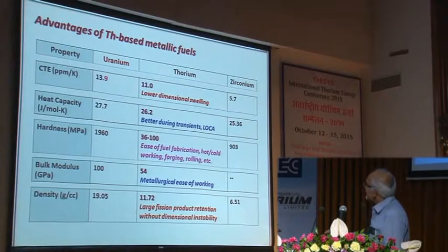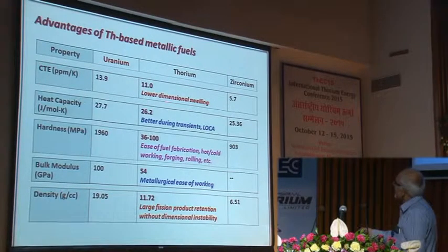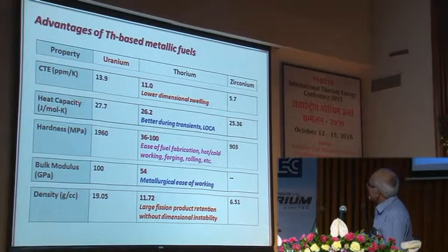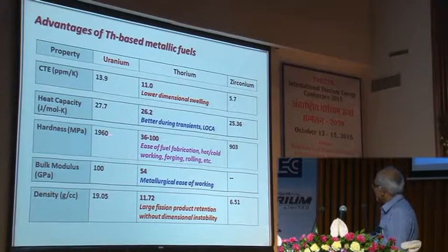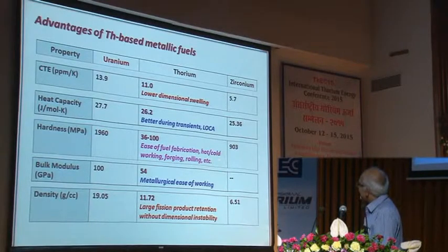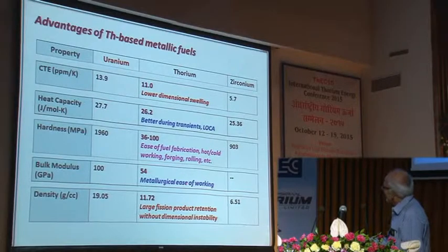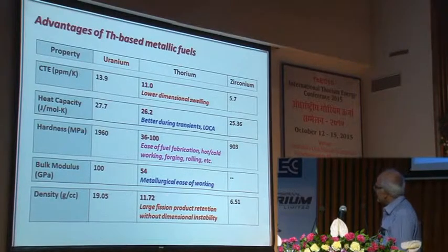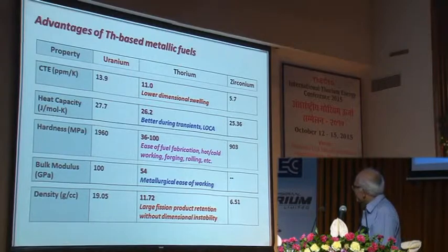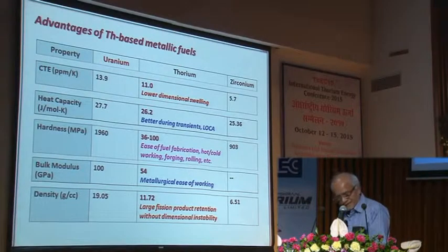The coefficient of thermal expansion is lower, so lower dimensional swelling. The heat capacity is marginally less, so that is better for transients and LOCA. The hardness is 36, much less than that of uranium. So this is the ease of fuel fabrication; hot, cold working, forging, rolling, etc. is possible. The bulk modulus is small, so metallurgical ease of working, and the density is low. Therefore, there is large fission product retention without dimensional instability.